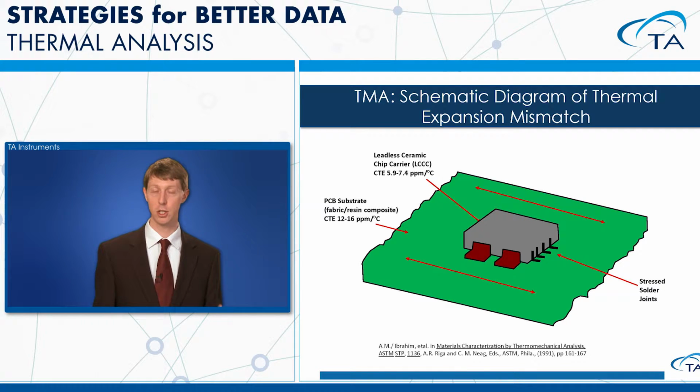Now, as a chip is used, it starts to heat up, cool down, heat up, cool down. If all of these particular materials don't expand and contract at similar rates or similar magnitudes, then obviously you're going to have one component that breaks free from another, or you're going to have the plastic component cracking, materials, multi-layer materials debonding from one another. So this is really where TMA is quite important, just to be able to match the various expansion rates of